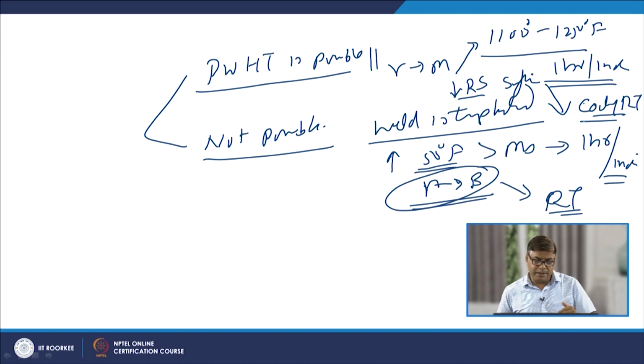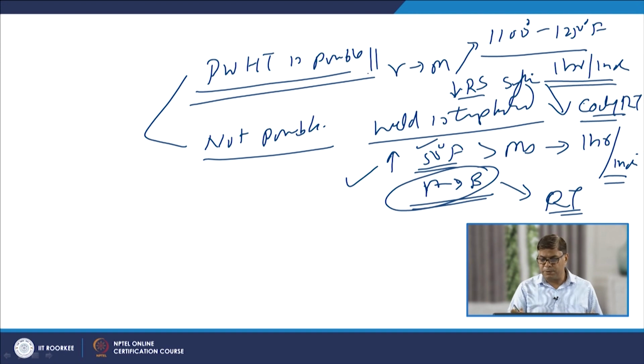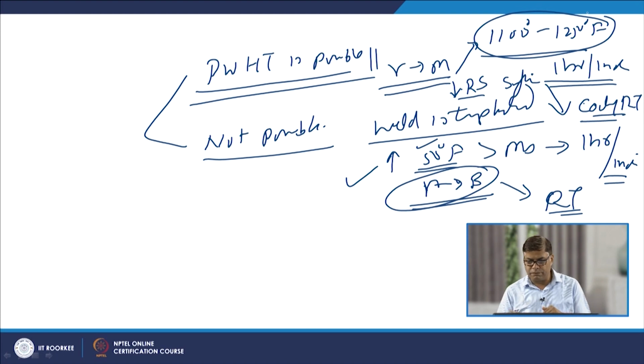In one case, when immediate post weld heat treatment is not possible, then after the completion of the weld, the joint is heated up to 50 degrees above the MS temperature, and in the second case, if the PWHT is possible, then we will allow the complete martensitic transformation by cooling down below the MF temperature, and then heating at this temperature for 1 hour will help to form the softer phases and relieve the residual stresses.